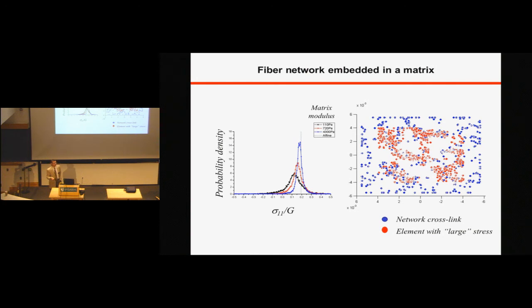Well, it turns out that there is another effect that kicks in, which we didn't expect, as follows. Think about how the network wants to deform. When you stretch it this way, it has a really large Poisson's ratio. So the network wants to squeeze, to get compressed, right? Now the network is actually embedded in the matrix, and the matrix has a much smaller Poisson's ratio. So when you pull, the network is actually squeezing the matrix. The matrix is expanding in the horizontal direction, the direction of the stretch, and is compensating, therefore, for the applied displacement in the horizontal direction. So you are effectively decreasing the mean stress in the matrix. This is why these PDFs actually shift to the left.